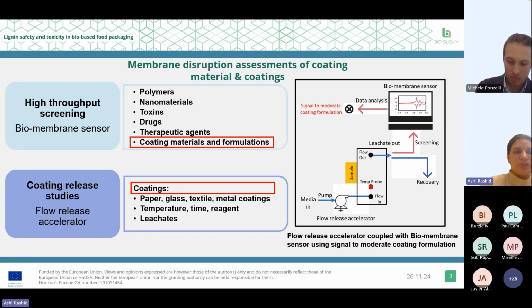The reagents which are generated after exposure to coating, and any leached out coating constituents, we call them leachate. Leachate from the release accelerator is then subjected to the biomembrane sensor for membrane disruptions caused by the leached amount, and this signals further tuning and moderation of the coating formulation following the SSbD approach.